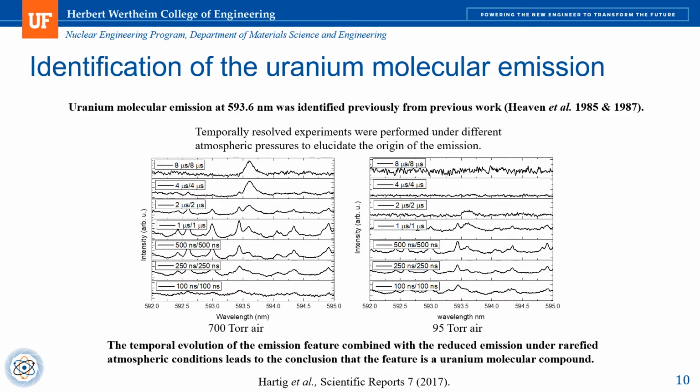Unlike a lot of the atomic measurements for looking at different isotopes with LIBS, we're not operating under rarefied conditions or under inert atmospheres, and we're actually relying on the chemistry of the material to react with the ambient atmosphere to generate a molecular emission, specifically for uranium, generating a diatomic molecule, uranium monoxide, that we're going to try to observe the isotope shift in.